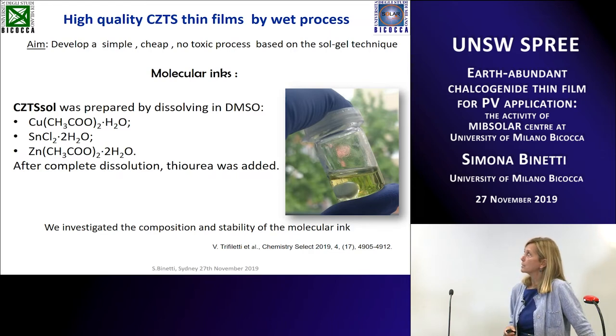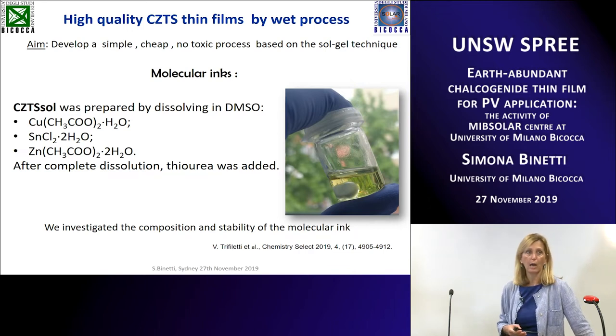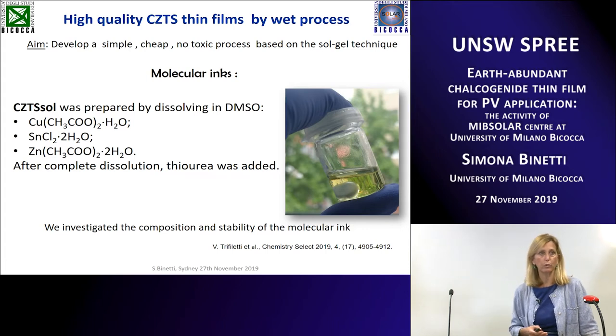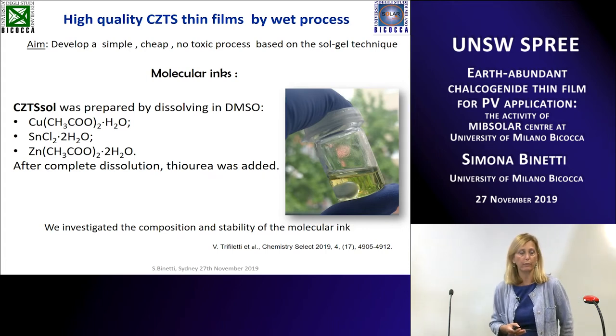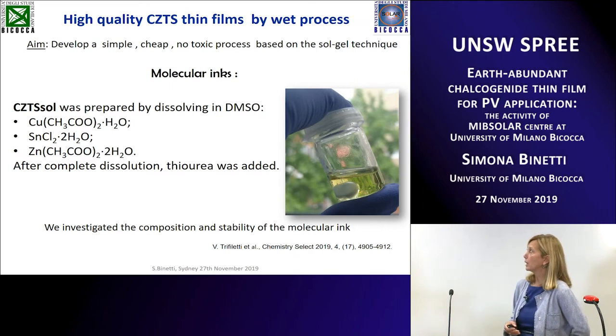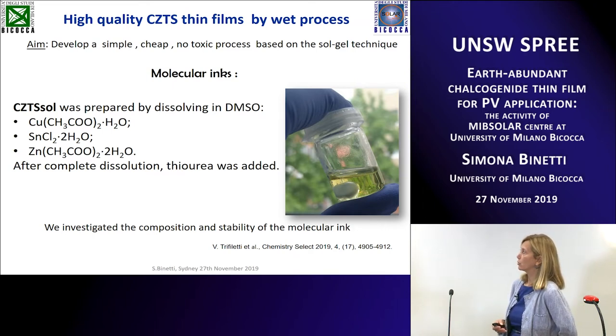non-toxic, simple and cheap process based on sol-gel techniques. So our idea was to prepare a molecular ink starting from acetates of copper and zinc and tin chloride. And then, after complete dissolution of these precursors, we added the thiourea. Thiourea was our source of sulfur because we wanted to introduce sulfur in another way, just putting it in the solution.